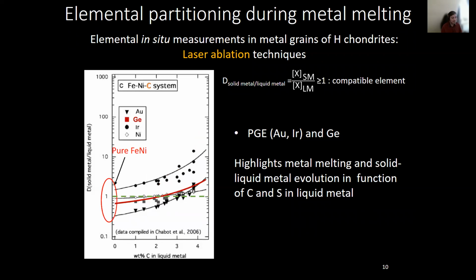And this is the same for, for example, carbon. And the difference of compatibility between these two elements during metal melting and crystallization is always similar, whatever the proportion of sulfur and carbon you are adding in the metal. This means that the first or the last liquid, depending on whether we are studying melting or crystallization, will always be enriched in germanium compared to iridium, meaning that the germanium to iridium ratio is a good tracer for these processes.